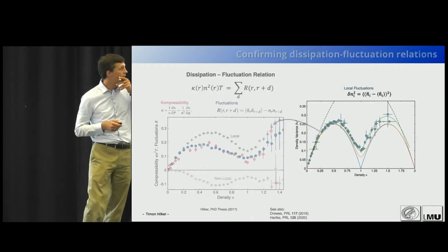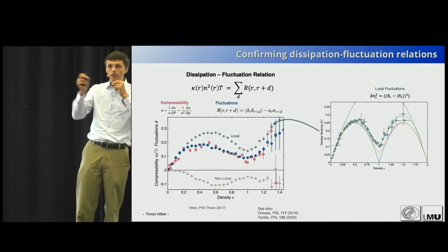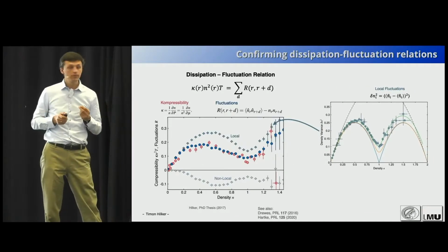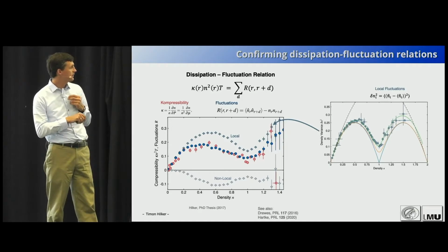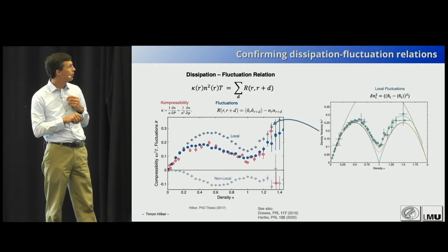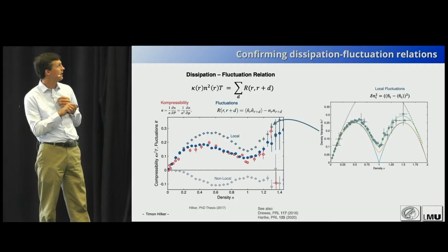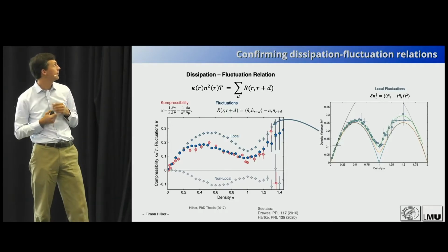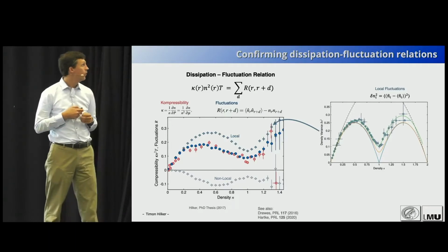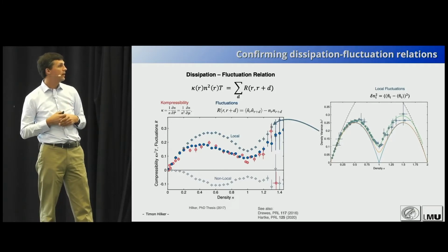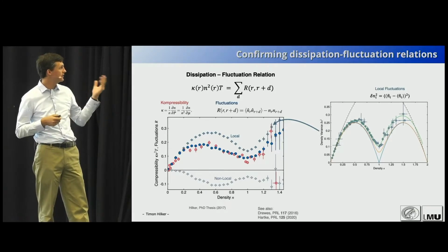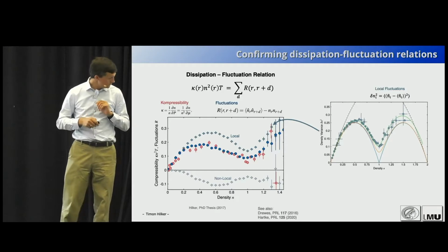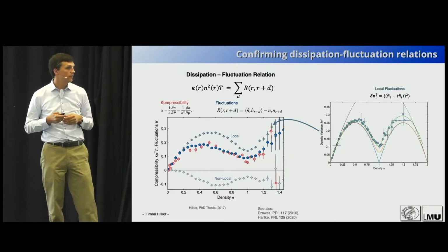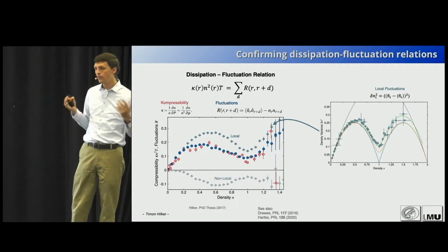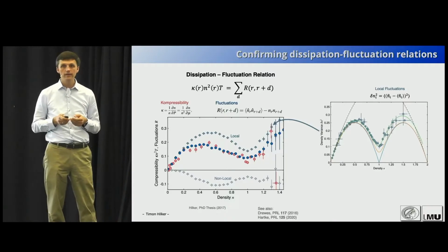But those are only local correlations. If we also non-locally correlate these pictures, we can in addition extract the sum of all the non-local correlations, and one can do nice checks where one adds these all up and confirms some fluctuation-dissipation relations, where the compressibility, which we can measure independently, and the temperature match up. And so that's a nice confirmation that these pictures really contain all the terms, and we're not missing anything that is relevant over larger distances.